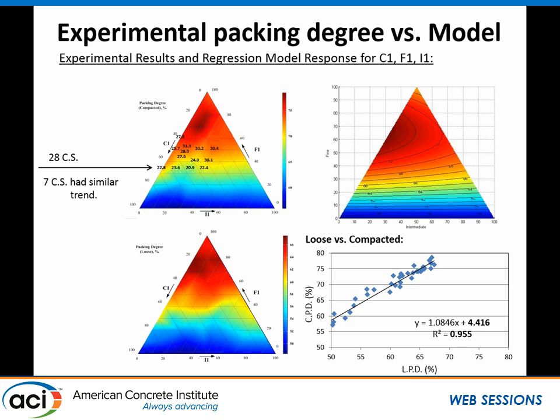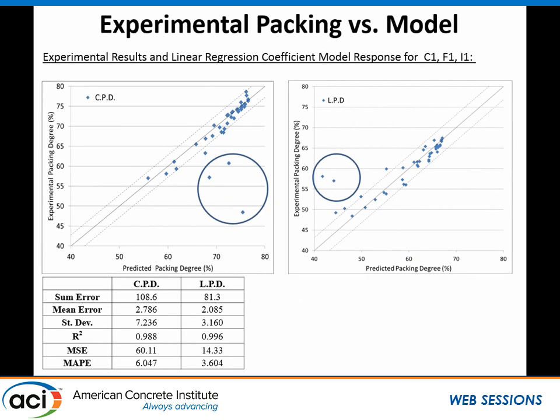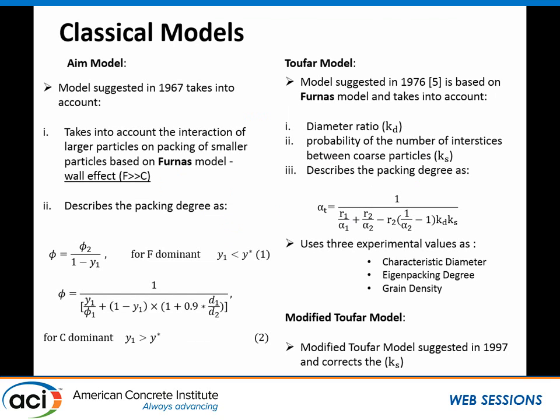And this is basically the model, a response model based on the actual experimental data. You can see the experimental packing degree versus the predicted packing degree of the model. What you see here is that the R square is really high for both of them. There are some points that don't fit the model, but the correlation is still high, which means we can rely on linear regression models later if we don't want to run the experiment.